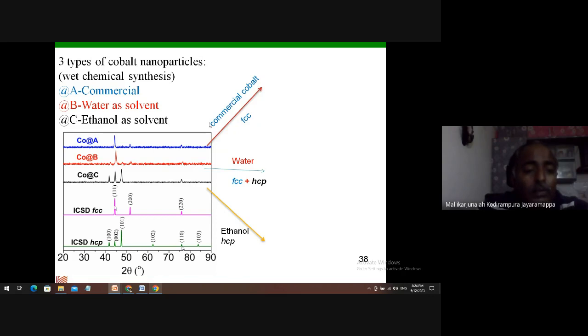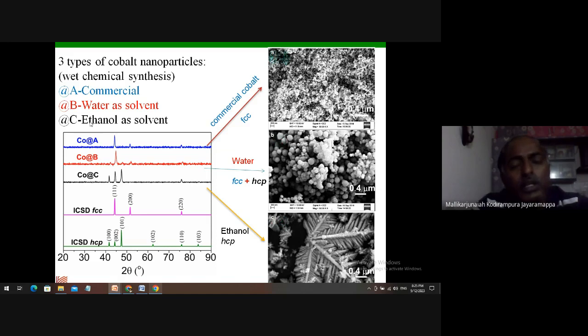Hence, whenever you record the XRD of your own sample, I will get two peaks. How do you really quantitatively tell whether that is due to the FCC phase or the HCP phase? It is extremely difficult to distinguish whenever we have mixed phases like this, as predicted here. For that, we prepared cobalt using different wet chemical synthesis methods. One, we purchased commercially available cobalt, we prepared another cobalt with water as a solvent, and the third system is ethanol as a solvent. We prepared them and recorded the XRD, and also recorded the SEM images.